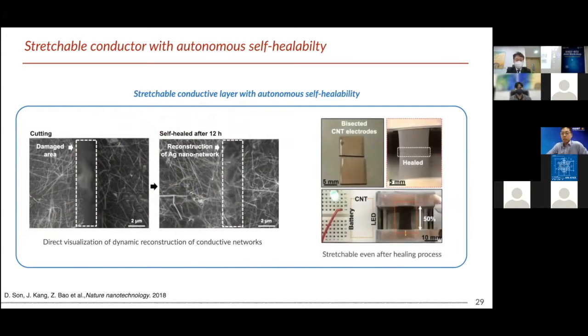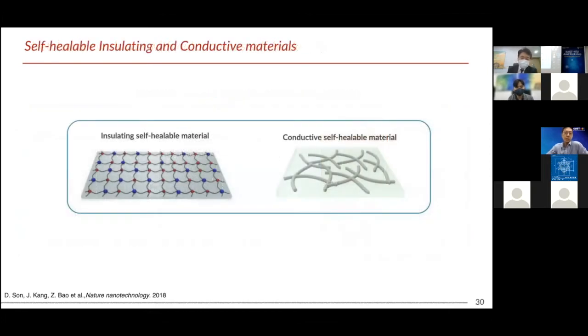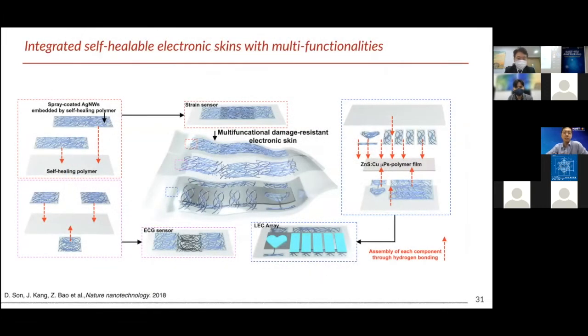And in order to confirm their mechanical healing, we fully cut their electrode and put it together. And after 3 hours, we found that upon stretching, they can still maintain their mechanical properties and also the electrical properties as well. So now we have a very nice insulating layer and also a very nice conductive material. And because of their mechanical robustness, we are able to fabricate this kind of integrated self-healable electronic skin with multifunctionalities.